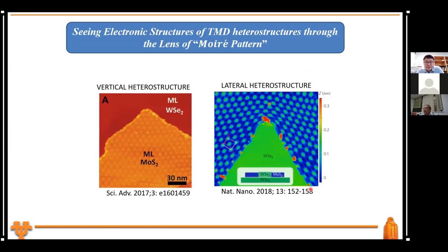Now I'm going to quickly go through this part. Some of you may have already heard this, that is the moiré pattern. If you have a lattice-mismatched system, then even if the two are well aligned, you're going to create a moiré pattern due to this geometric interference. And then you can also have a lateral heterojunction. In this case, this is a lateral heterojunction, with the MoS2 on the top, and then the core is the same as the substrate. You see no moiré pattern, and then this MoS2 shows the moiré pattern, but because of the strain created by forming this lateral heterostructure, the moiré pattern truthfully responds and shows this distorted moiré pattern.